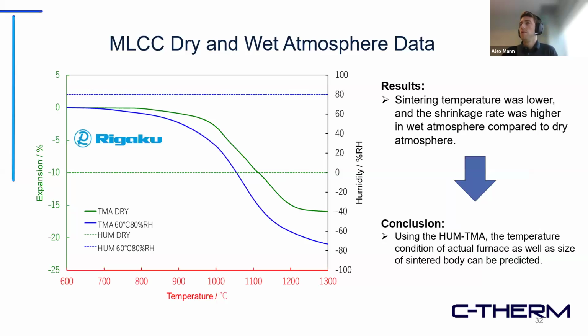As we can see here, the blue is the one that was wet and the green was dry. The blue did begin to sinter sooner, and it sintered at a much greater rate. And at the end, it had shrunk more. That's kind of the brief takeaway you can see just by reading this.